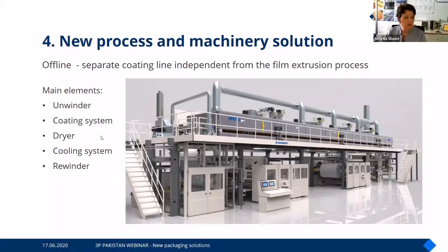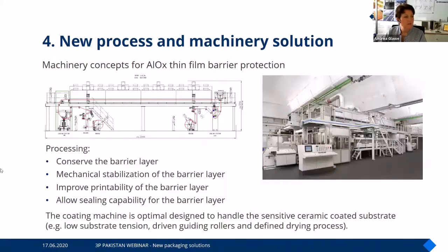It can be a roller, slot die, comma bars, knife coating, whatever. You see here on top the dryer, which is necessary to cure, to dry, to cross-link the coating layer. At the end, usually you need to cool down to a temperature which is reasonable before you rewind the finished product. This is at least the standard solution for a coating line.